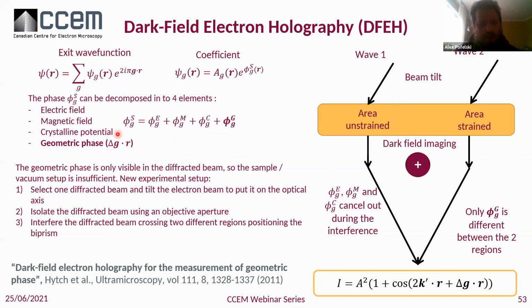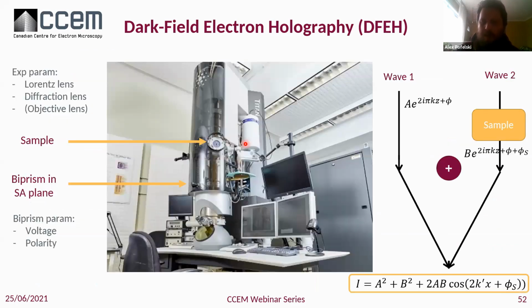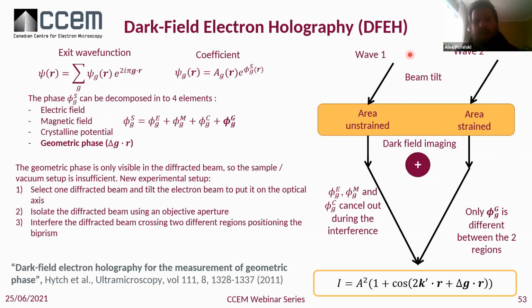In addition, we want to see the delta G, so the variation of the G vector. So putting this into vacuum is not that of interest, especially if you go in the diffracted beam, you will see the zero beam. So what we're going to be doing here is making the interference between two areas, one area that is strained, one area that is unstrained. The unstrained would have 0, the strained would have a certain delta G.